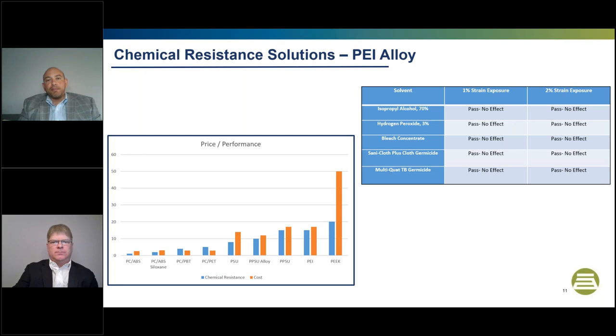So once the OEMs are ready to spend more per pound for their housing, we're ready with a series of alloys. And this is a quick alloy. This is a polyetherimide alloy. Trade name is going to be Ultem, where we created this formulation, easily colorable, molds great. It's going to have great inherent flame resistant properties. And that's great because if you don't have to add FR packages, you're going to retain the mechanical properties. And we tested it to a whole series of chemicals, and this is just 4 or 5, and there was no effect at 1% or 2% strain.